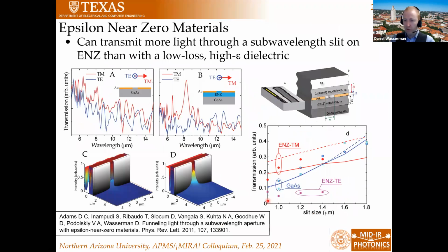We can also use these materials as epsilon near zero materials. So it turns out that if you can fill a gap in a sub-wavelength slit with epsilon near zero material, you can actually strongly enhance the transmission through this sub-wavelength gap. So this is the peak associated with the ENZ transmission through a sub-wavelength gap. This is experimental data, and basically what we showed is that you can beat the transmission through an undoped high index material using this, realistically rather lossy, but epsilon near zero material in a sub-wavelength slit.